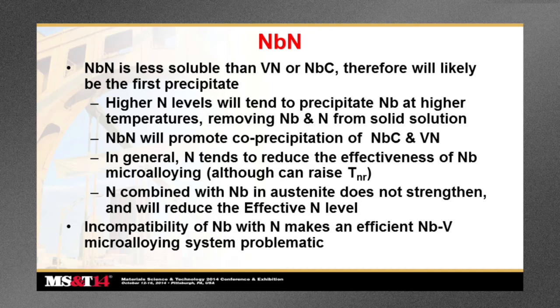Niobium nitride will promote co-precipitation of niobium carbide and vanadium nitride in the austenite, which is where you do not want it to occur. So in general, nitrogen tends to reduce the effectiveness of niobium microalloying, although it can raise the T sub NR temperature if that's your desire. But most niobium alloy designs are optimized with as low as possible nitrogen rather than high nitrogen. Nitrogen combined with niobium in the austenite does not strengthen, and it will reduce the effective nitrogen level.